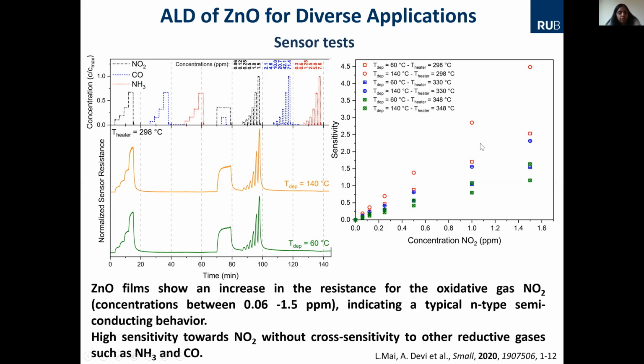This is because the crystallinity increases, and as I said, it's an oxygen deficient surface. The number of oxygen species, be it OH, O, O2 minus, all of them are higher at higher temperatures compared to low temperatures, and this is why the sensitivity is higher. So you can see, just by tuning the temperature, you can actually activate the surface. And in this case, as I said, we checked as a function of temperature with different gases.